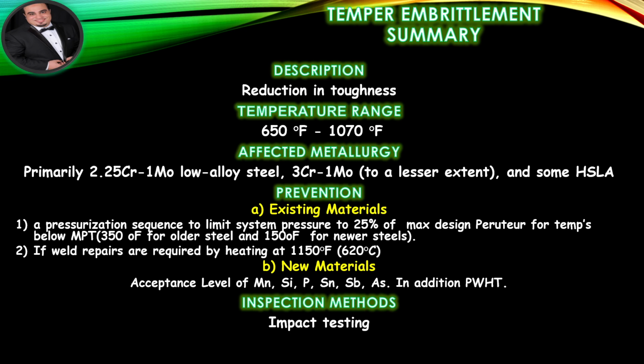Prevention. For existing materials, a pressurization sequence to limit system pressure to 25% of maximum design pressure for temperature below a minimum pressurization temperature, 350 degrees Fahrenheit for older steel and 150 degrees Fahrenheit for newer steels. If weld repairs are required, heat at 1150 degrees Fahrenheit. For new materials, acceptance level of manganese, silicon, phosphorus, tin, antimony, arsenic. In addition, post-weld heat treatment. Inspection methods: impact testing.